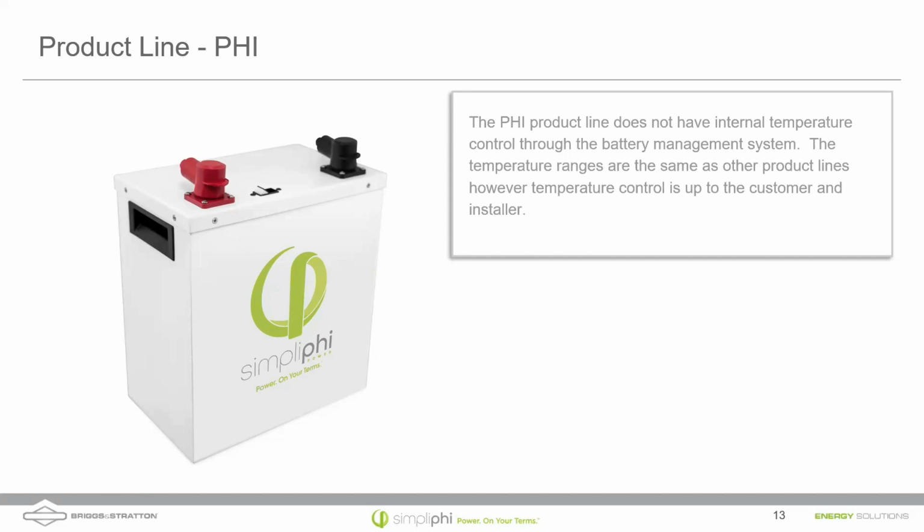It was a lead acid battery, and it was a deep cycle battery. And I was in a location that was so cold, the battery actually froze and burst, and that's because it has water inside of it. And so even with the sulfuric acid in there, lead acid batteries can actually get damaged and bulge out if they freeze. Lithium batteries, they don't have this problem, but as Daniel said, you want to make sure that you turn the charging equipment off if you know that the system is going to be very cold.